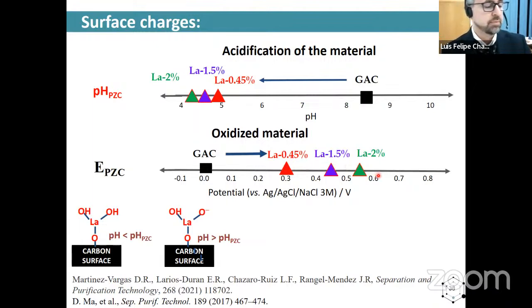So then the increase of this value for the modified carbons implies that they will require much higher polarization values, or much higher energy, to polarize them, which is a disadvantage for the process. And these higher polarization values are necessary to change the surface excess and also to remove fluoride.